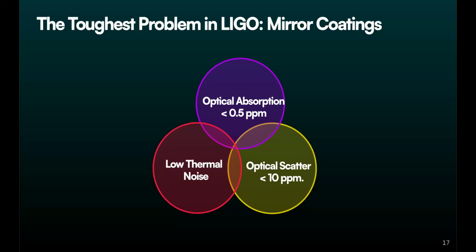But the reason it stops is because there's some dissipation. So the acoustic mode phonons in your wine glass travel around in your glass and they couple to the background heat bath, and some of the energy goes into the other modes of the glass. And so you are dissipating your energy into those modes. And because you can dissipate energy into your modes, it means noise from those modes can come backwards into the mode that you care about.